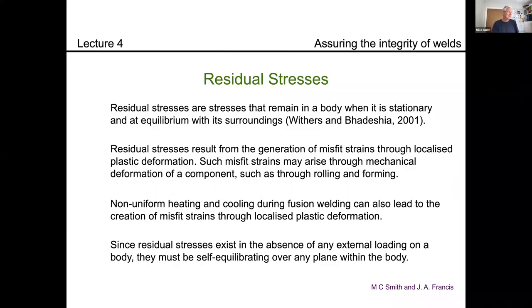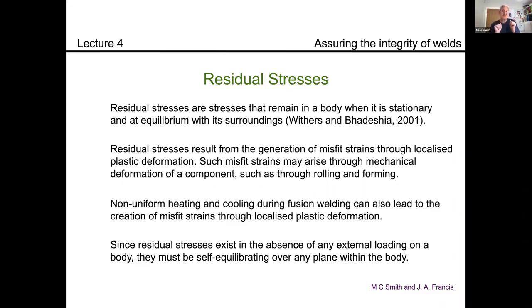One important thing about residual stresses: because they exist in the absence of any external loading, they must be self-equilibrating over any plane within that body. If they're not self-equilibrating, there's a net load, which means the body must be accelerating. So residual stresses: no external load, self-balancing across any plane within the structure, caused by plastic misfits. A classic example is a children's toy where you bang a wooden peg into a hole that's slightly too small. Banging the peg in causes the material around the hole to go into tension and the peg itself is put into compression.